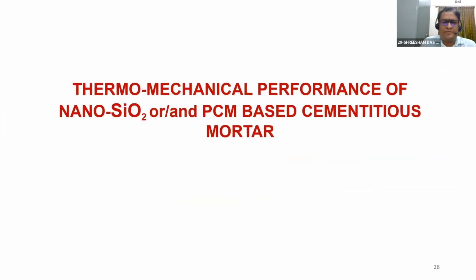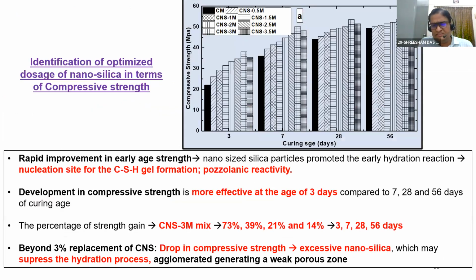Now, the thermomechanical performance of nano SiO2 and PCM based cementitious mortar. This is my compressive strength. I have spoken about this in many presentations; you can see some of the recordings on YouTube or some of the papers, so I will skip this. The moment you add nanoparticles, I am getting a tremendous increase in the compressive strength, and that too at the age of 3 days itself. That is the advantage of adding a very small percentage of nanoparticles.